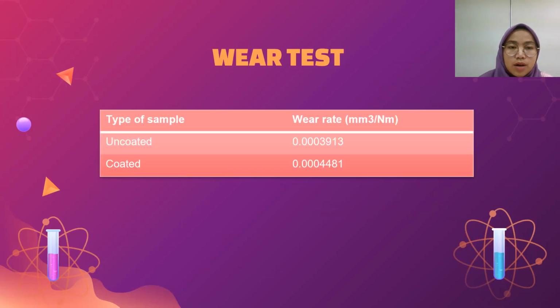For the wear test, the uncoated sample has a higher wear rate compared to the coated sample, which are 0.0003913 mm3 per Newton meter and 0.0004481 mm3 per Newton meter respectively.